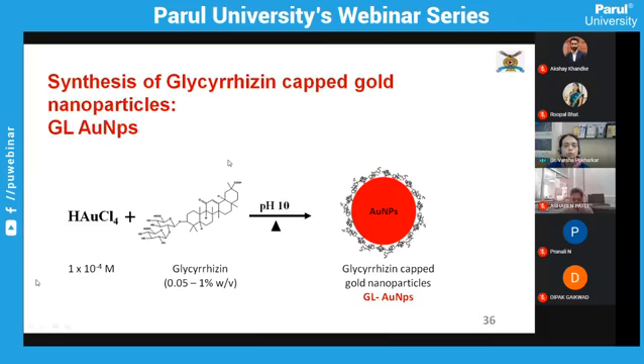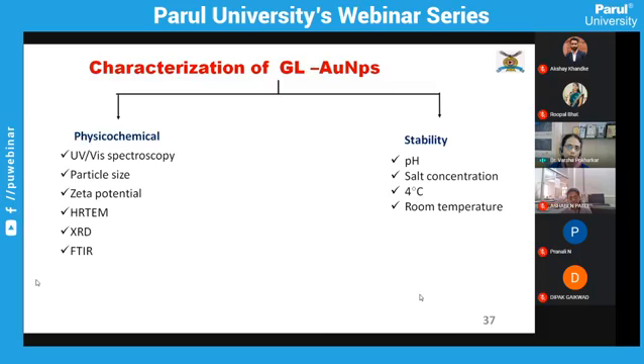The synthesis of glycyrrhizin capped gold nanoparticles was a pretty simple one-pot method, wherein we took hydrochloroauric acid and glycyrrhizin in different concentrations at pH 10 and heated the solution for 5 to 10 minutes. That resulted in a ruby red colored solution of gold sol, which represented the glycyrrhizin capped gold nanoparticles. We then went for the physicochemical characterization, as well as the stability, of these prepared gold nanoparticles, obtained by reduction using glycyrrhizin as a reducing and stabilizing agent.